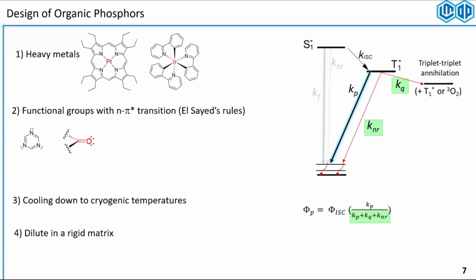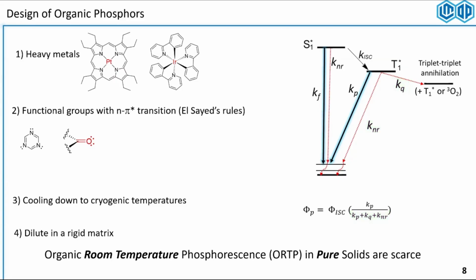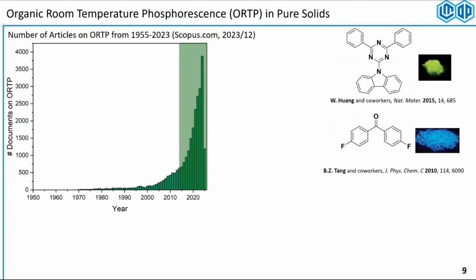For example, triplet annihilation. Two triplets would like to meet each other, one going to the high-lying singlet excited state, one losing energy down to the ground state, right? Oxygen is a triplet state. In its ground state, the oxygen gas is a triplet molecule that will react very prominently with triplets that we generate. And of course, non-radiative decays in the microsecond to second lifespan of these triplet excited states become really important as well. So we have to cool it down either to cryogenic temperatures or very solid matrices, and also normally dilute them in a matrix so that these triplet annihilations don't occur as well. And you can see from these design principles that making an organic compound phosphoresce at room temperature without heavy atoms is going to be really scarce and difficult to do.